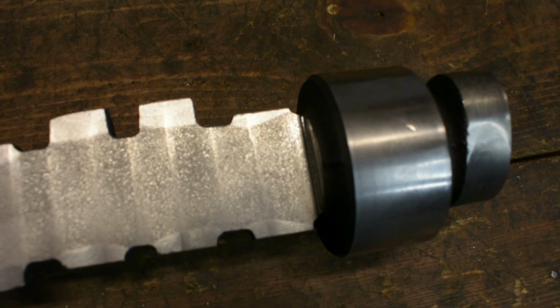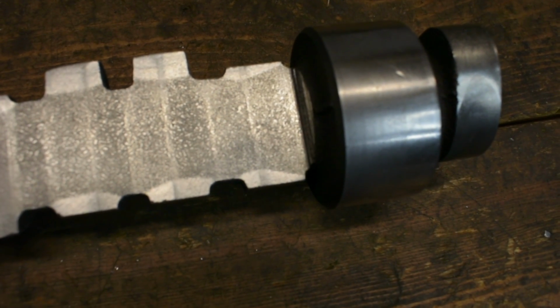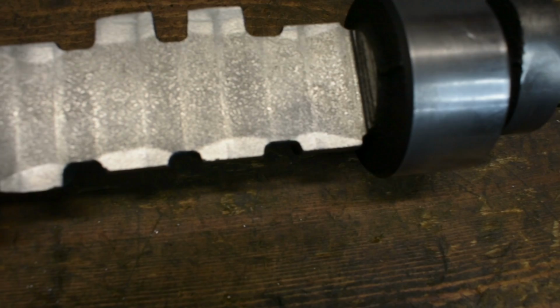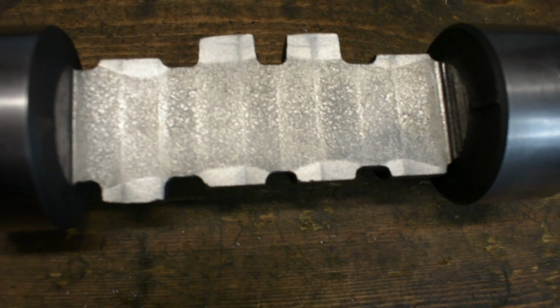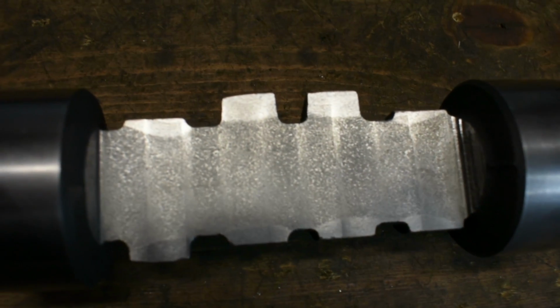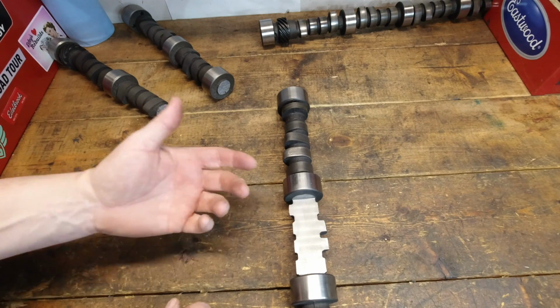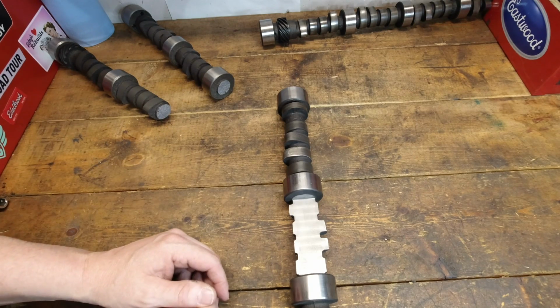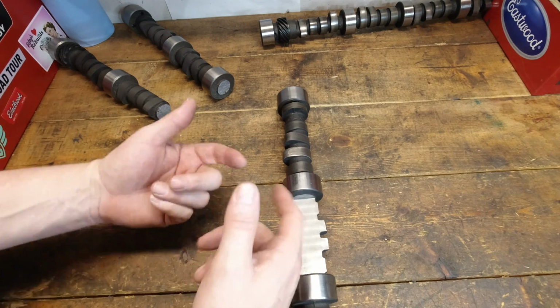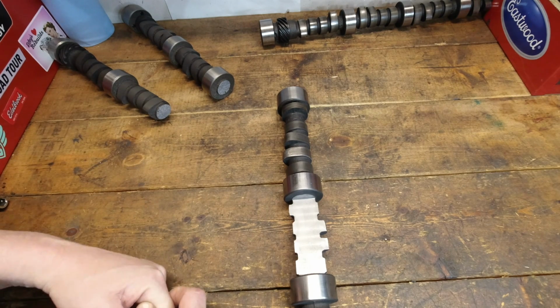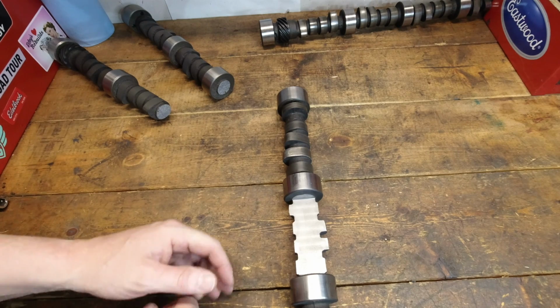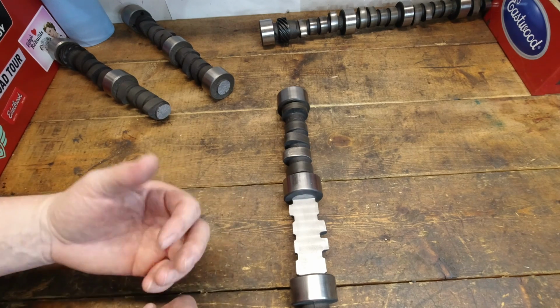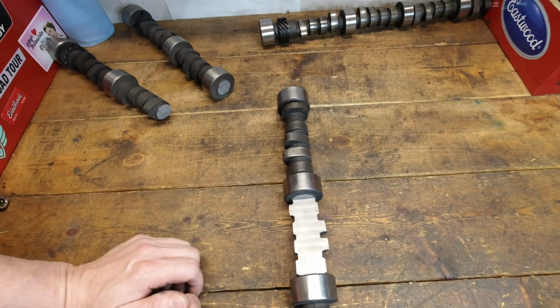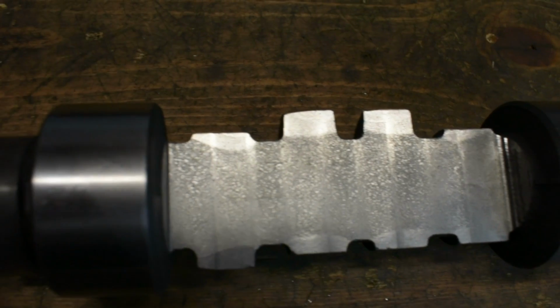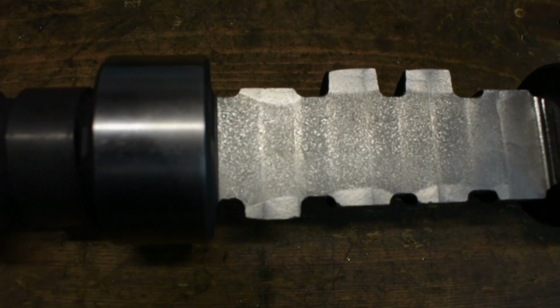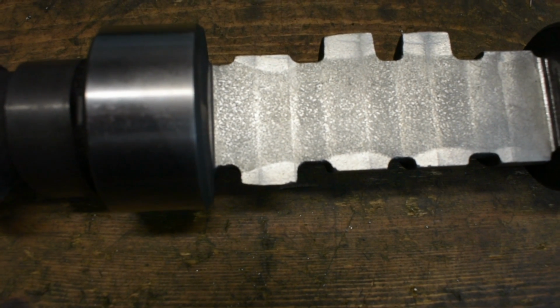And if you look at it and see how that kind of looks, it's not even. They don't get heat treated through there evenly. It's not an exact process that goes through there. The material may take it a little bit differently, accept the heat a little bit differently. The cool down period may be a little bit different. If they quench it, like on a tempered iron core, in a salt bath or something like that, those are all definitely little things, but it's never going to be a perfect line through there.